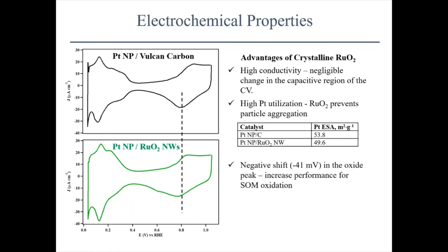What we did see that was interesting was that there was a negative shift in the oxide peak. This tells us that the ruthenium oxide is leading to the platinum becoming slightly more oxophilic, meaning that it's a little bit easier to oxidize the platinum with the ruthenium oxide than with the Vulcan carbon. So this could be a combination of the electronic interaction between the support and the platinum. That's one possible factor. Or it can also be the fact that the support itself leads to the presence of oxide species at the interface, which we could be detecting also in the CV, meaning the physical interaction and the existing oxide species of the ruthenium oxide substrate may also affect the CV itself of the platinum.